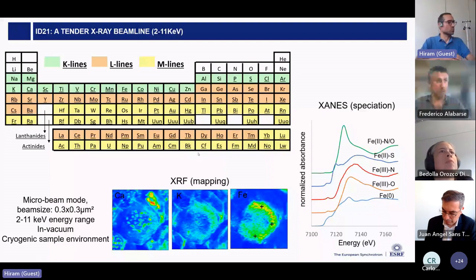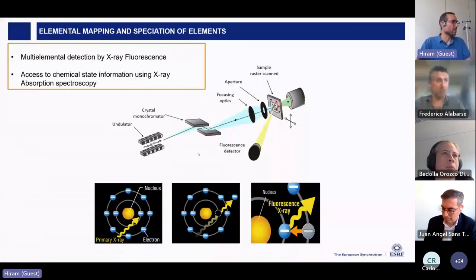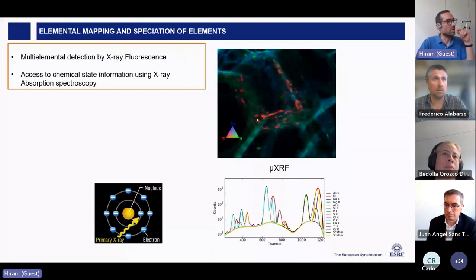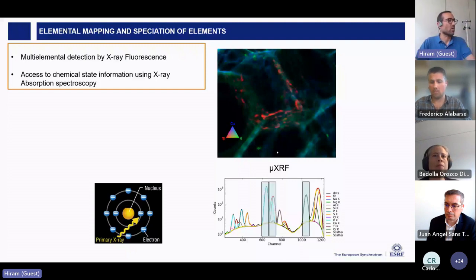So just to summarize our technique, well, we have a monochromator to select energy. We can scan it. We have KB focusing optics to get a small spot. We send the X-rays into the sample, and we collect an X-ray fluorescence spectrum in each one of the pixels of our scanned sample. Then after, we can display them through the creation of regions of interest in the detector and overlay them, in this case titanium, calcium, potassium, or we can do a fitting and separate them.